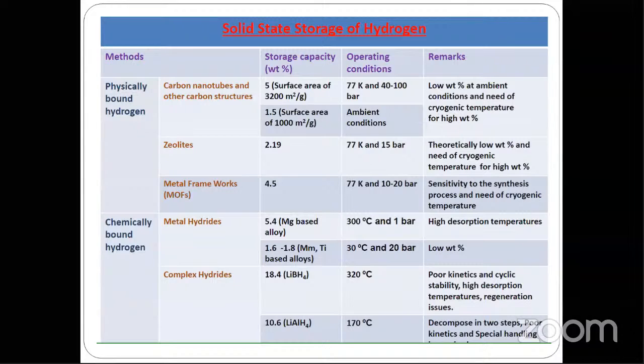Again, if you see the zeolites, again the same problem. You have to go for cryogenic temperature around 77 Kelvin and 15 bar pressure requirement. Again, it's a low weight percentage and needs low temperature. The MOFs also, again, you have to go for cryogenic temperature to have high storage capacity up to 4.5%.